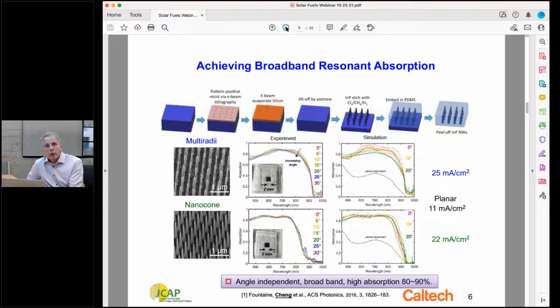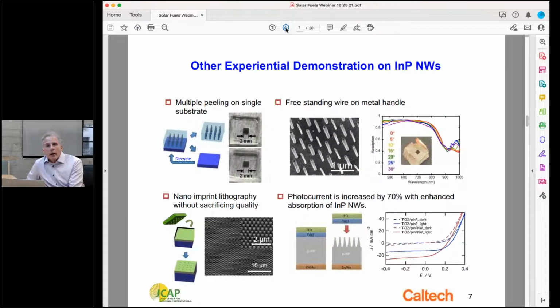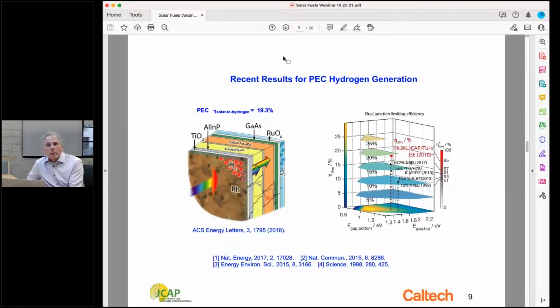So that's an example of how nanostructures could be used to enhance absorption. I'll now move on to describe work on this device, which was a tandem device with a tandem photoelectrode whose band gaps were tailored to span the solar spectrum and produce the photovoltage needed for photoelectrochemical water splitting, using a rhodium hydrogen evolution catalyst and a ruthenium oxide water oxidation catalyst.